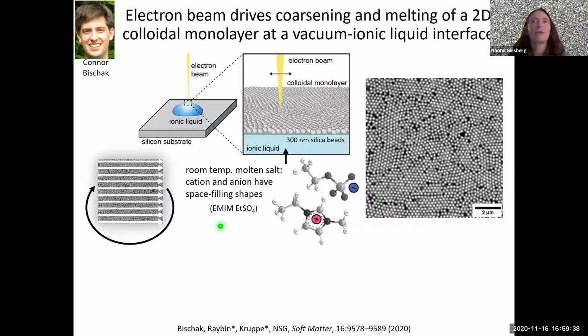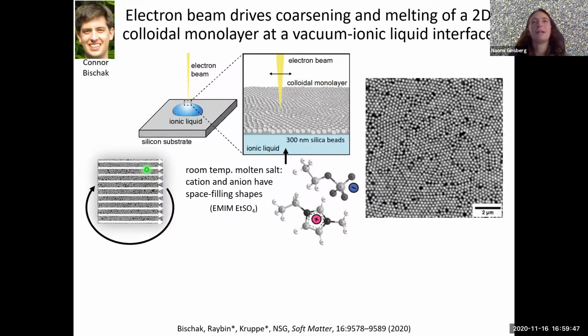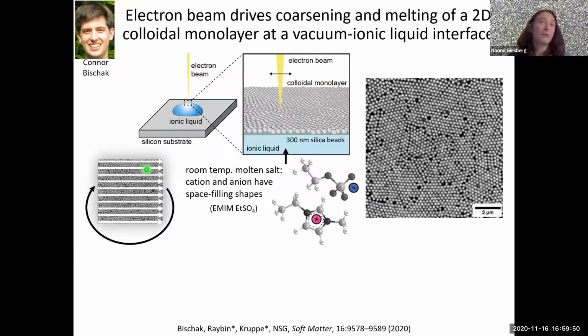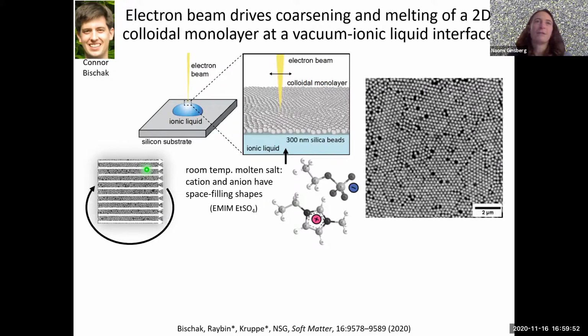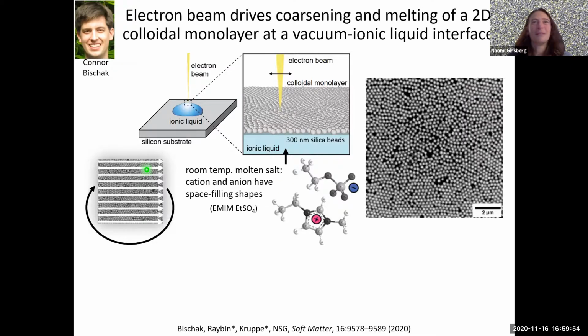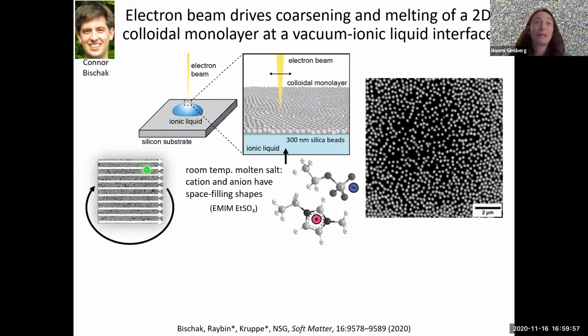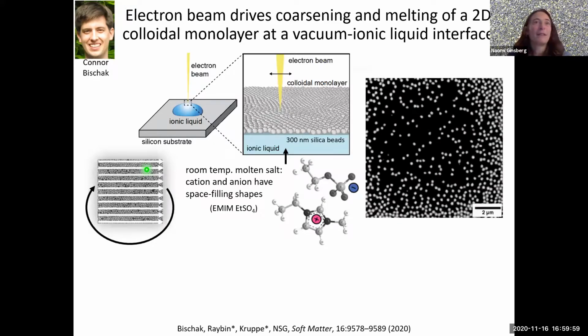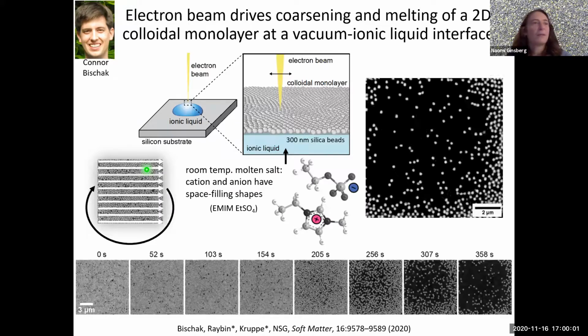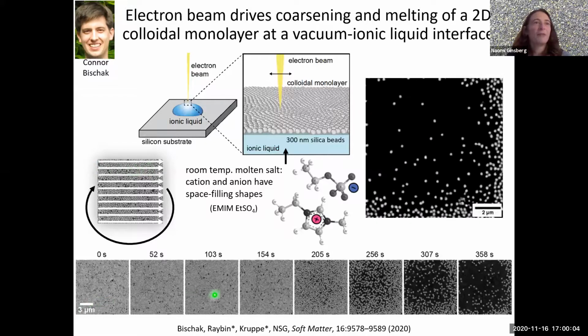We repeatedly raster the electron beam, so it visits one particle or one pixel once per movie frame, and here's what we observe as we make this sort of movie. And of course, our goal in making these movies is to then try and explain what's happening. Okay, so here's a montage of these dynamics, and you can see that we certainly started at a higher density and then moved to a lower one. So we want to be a little bit more quantitative than that.